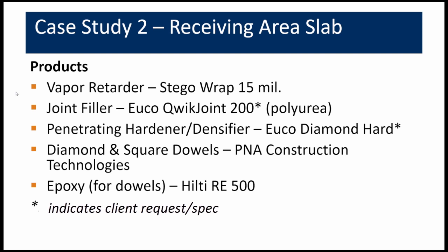I did use the polyurea on a project on Hilton Head Island on some slab repairs there, and we did have issues with the air voids that Kit mentioned. In that instance, the air voids that I had seen were a little bit larger. I think on that case also, when they shaved the joint, it was slightly concave rather than perfectly flush with the epoxy. So since then, I have gone to using the epoxy instead of polyurea.